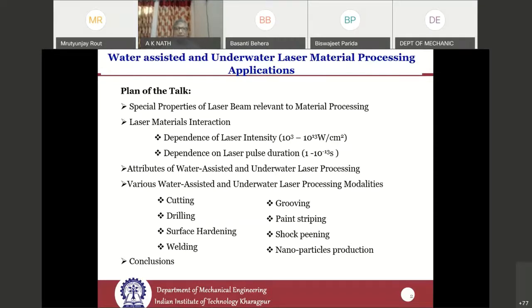And since we are dealing with the various materials, we must understand what is the basic mechanism of interaction of laser beam. And it has been seen that it has got very strong dependence on the laser power density or intensity, which is expressed as watt per centimeter square. That is the watt per unit area of the surface, what is the power. Then also it has been seen that how the material and laser beam interact depends on the laser pulse duration. Whether we are using a CW laser or pulse laser, and in pulse laser, we have got nowadays available millisecond, microsecond, nanosecond, picosecond, and femtosecond lasers.